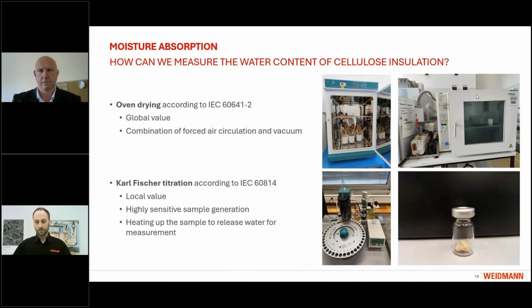What you do is you take your sample, you weigh it in the conditioned state, then you go into the forced air circulation oven, dry it for 1 day, then dry it in the vacuum oven to reach minimum value, and in the end, weigh it again. The difference in weight will then be the water that was removed and can be calculated back to a water content. Now, this is a global value that just says this part of the sample had this content, but there is no possibility to determine the exact location at a certain water content.